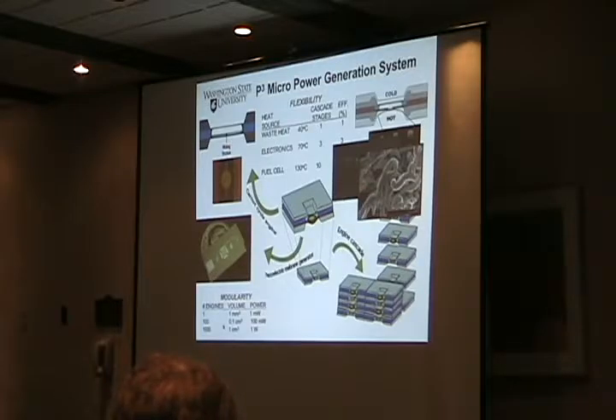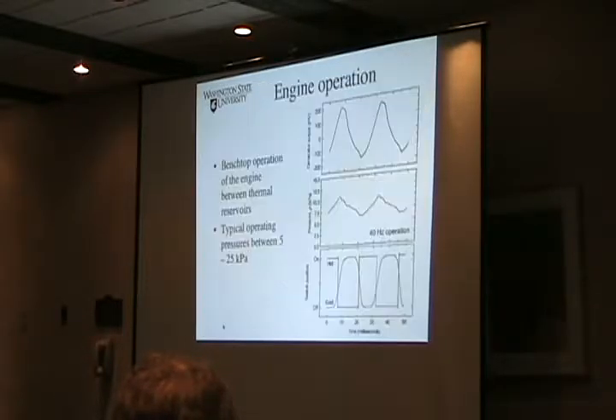Exactly. And when we do our hot and cold switching, we're actually switching around 15 to 20 degrees C, and we try to get small delta T's. We're trying to scavenge some low-grade heat, dump to ambient instead of cold temperatures. So you eat sort of half or three-quarters of the delta T of thermal conduction. Yeah.